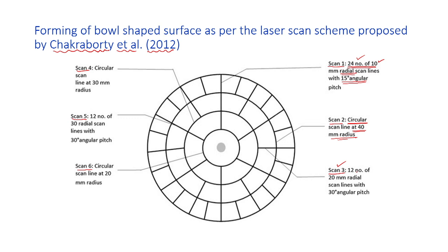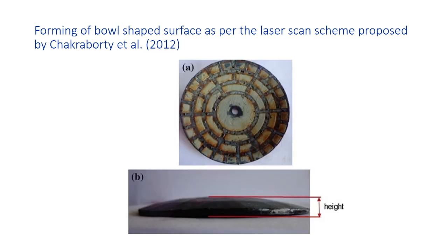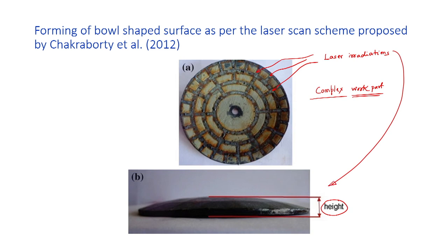The third group of scanning comprises 12 radial scan lines of 20 mm with an angular pitch of 30 degrees. In a similar way, the scan 4, scan 5 and scan 6 group of radial scannings and the circular scannings were applied, and after applying these scans, you can notice a very good quality dome shaped complex work part was generated. So, this is a complex work part with various irradiation patterns. So, all these are the laser irradiations. And after applying these laser irradiations, we got a dome.